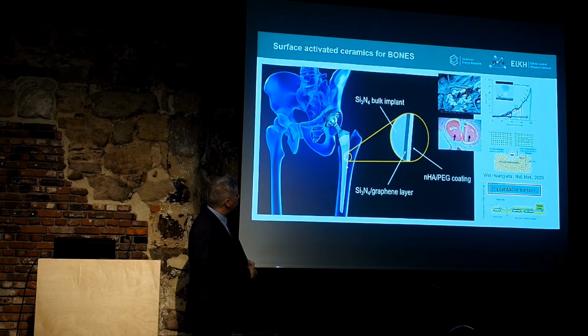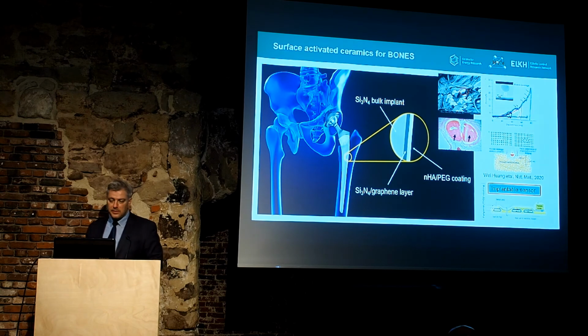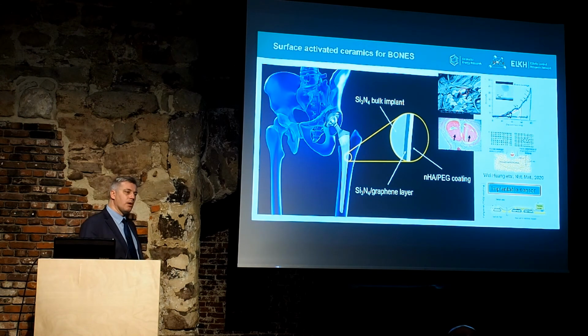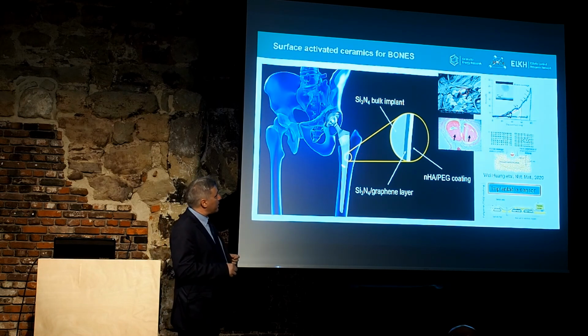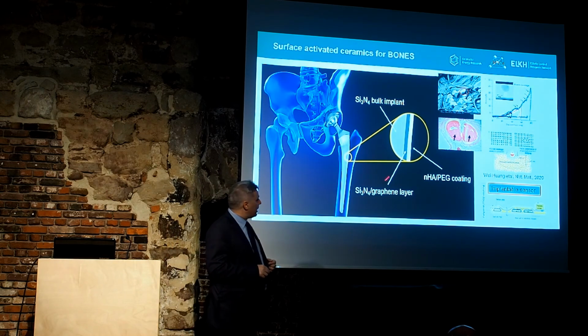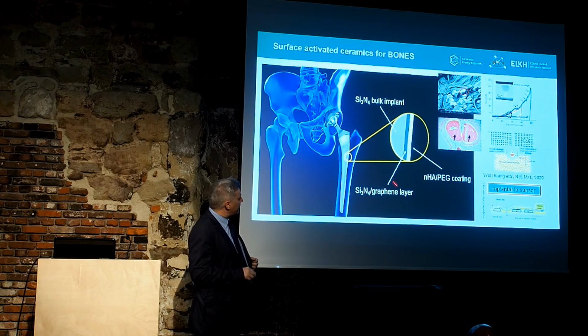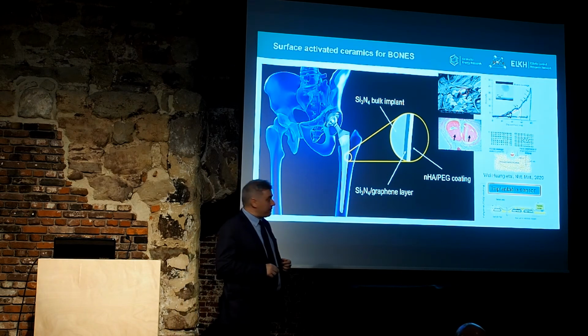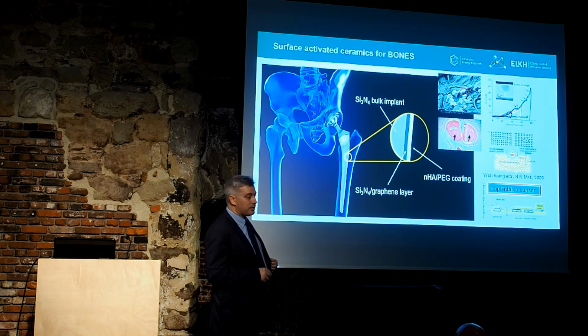We want to replace medical implants like hip joints made from titanium aluminium vanadium alloys. We are aiming to replace the harmful joints that cause contamination of vanadium or aluminium in your body, which is harmful. If we can change to silicon nitride, this is a new concept: we can provide a multilayer, granular structure, having at the surface a silicon nitride graphene layer, and we can also apply nanohydroxyapatite.